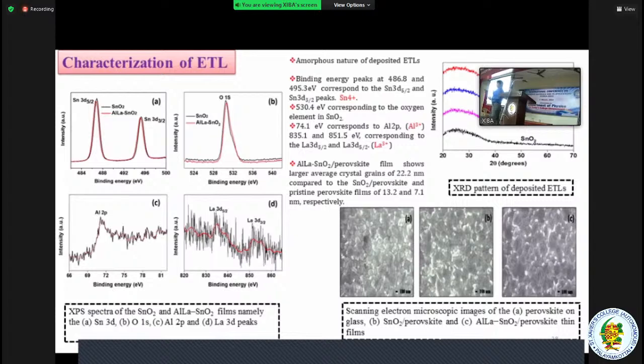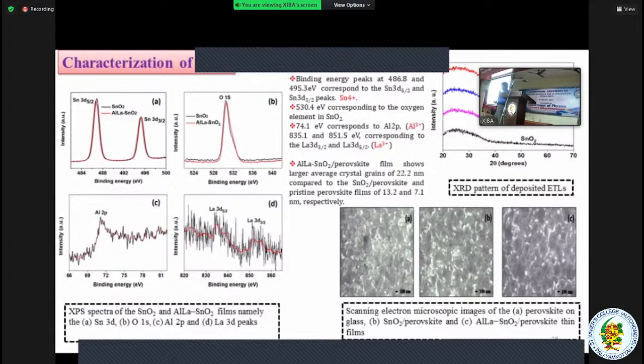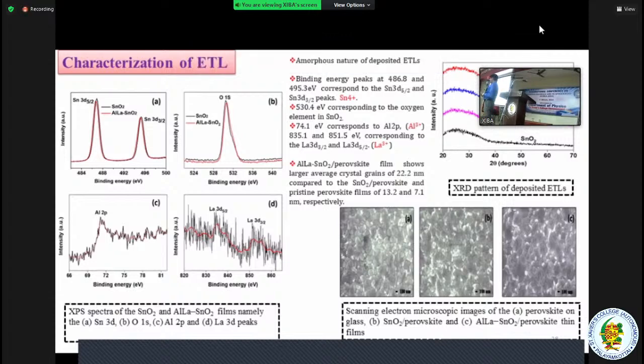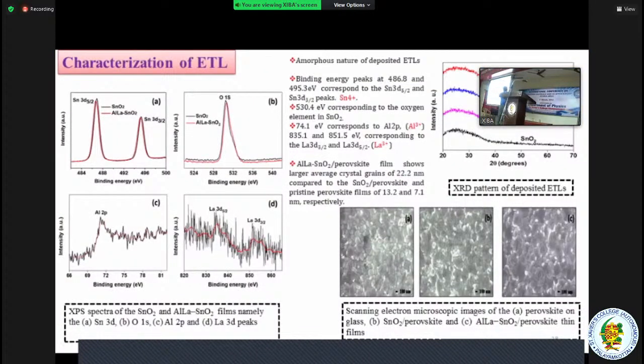We have to do many characterization activities. Through XPS, we can find out the presence of tin, aluminum, and lanthanum. And similarly, the X-ray spectra of this material. These are the SEM images. In these SEM images, it is clearly indicated that the aluminum lanthanum co-doped tin oxide is pinhole free, and moreover, the grain size is bigger when compared to this and this, the pure tin oxide. This is important. Unless we have a pinhole free layer, we cannot expect any conversion efficiency. Next.